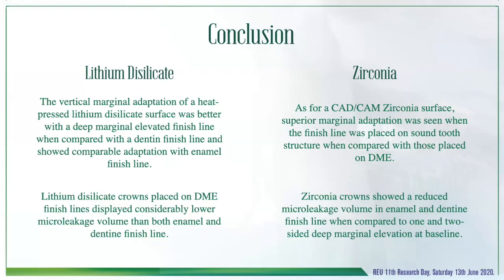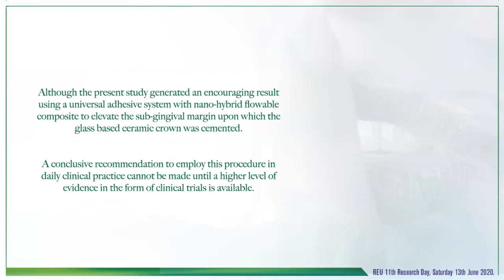As a conclusion, lithium disilicate on a composite finish line has better vertical marginal adaptation than dentin and had comparable results with enamel. As for microleakage, it showed better results. As for the zirconia, on the other hand, it showed better vertical marginal adaptation and less microleakage than the deep marginal elevation.